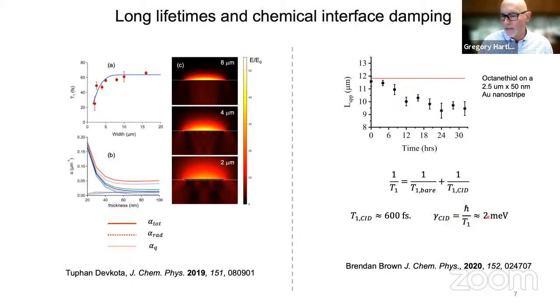And it turns out that it's a very small effect, right? If you look at particles that Stefan did with Carsten Sonnichsen a few years ago, chemical interface damping is about 20 to 30 millielectronvolts. We're about 10 times, 20 times smaller than that. And the reason is that these structures are very large, so the surface to volume ratio is not very good, right? The metal particles that you look at are much smaller, so the surface is a much bigger effect, and chemical interface damping is bigger. These structures are too big to give you much chemical interface damping.